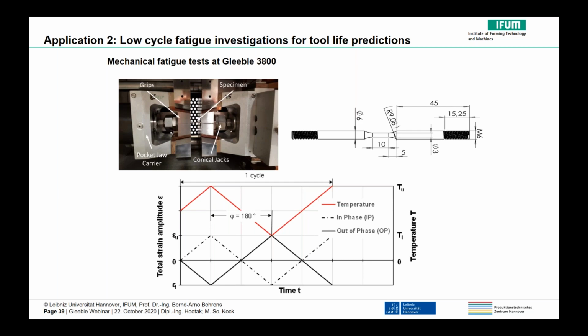The tests were carried out, as mentioned, in the physical forming simulator system Gleeble at the IFUM to parameterize the model. During the LCF tests, the specimens were cyclically loaded with a constant strain amplitude isothermally in atmospheric air. In addition, so-called in-phase as well as out-of-phase thermomechanical fatigue tests were performed, where the temperature oscillates between 300 and 750 degrees C and strain are in phase or have a shift of 180 degrees, respectively.